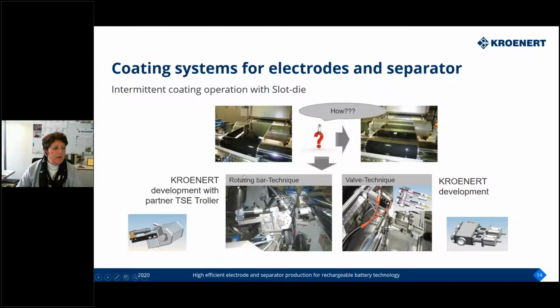I already explained that we have a special intermittent die with the bar in the center, but we also have a valve technology. We also followed that valve technology for some very critical slurries, which, due to the particle size, tend to agglomerate. In this case, the rotating rod inside the die causes some problems. And in such a case, we also introduce our customer to the valve technology.